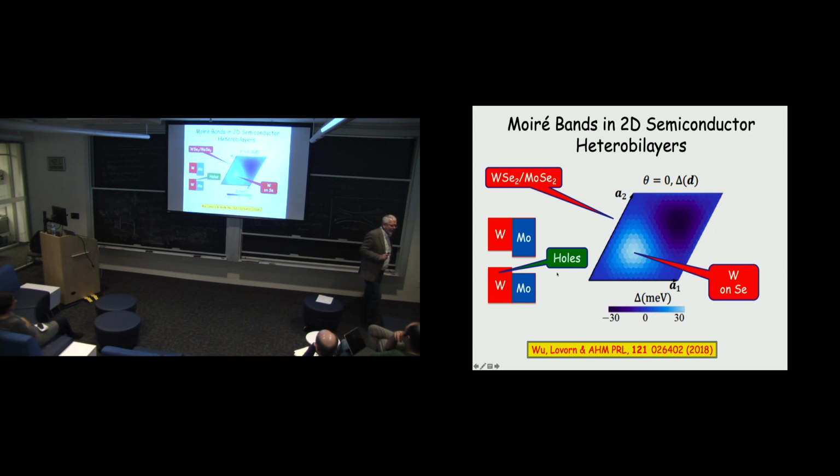Normally for every momentum, you have two spin states, but it turns out this semiconductor doesn't have inversion symmetry, and it has rather strong spin-orbit coupling. So at every momentum, the double degeneracy that you normally associate with spin is lifted. And so the states at the top of the valence band are not spin degenerate.